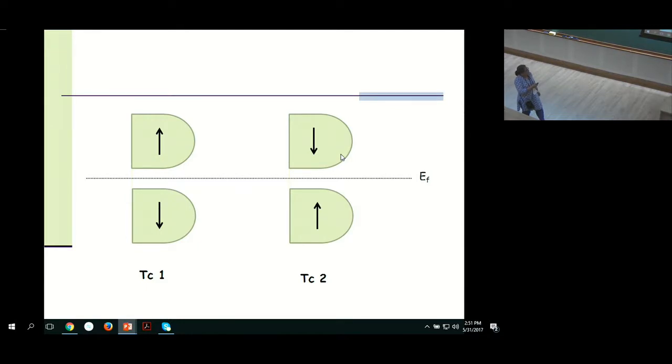Because it's half filling and your Fermi level is over here, there is hopping between the sites, and because of superexchange interactions you gain maximally in the antiferromagnetic configuration. This is why the G-type, totally antiferromagnetic solution is the one stabilized in all the calculations.